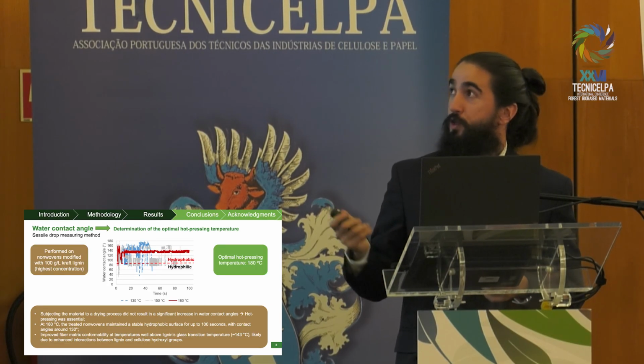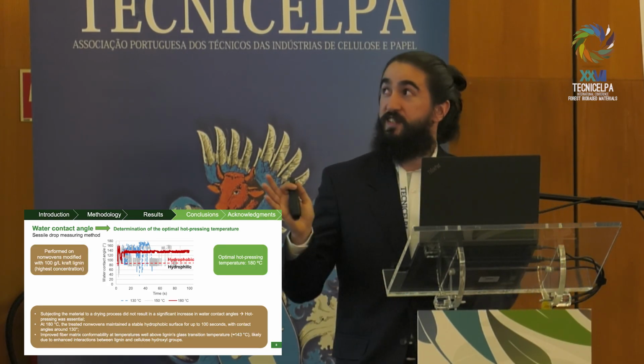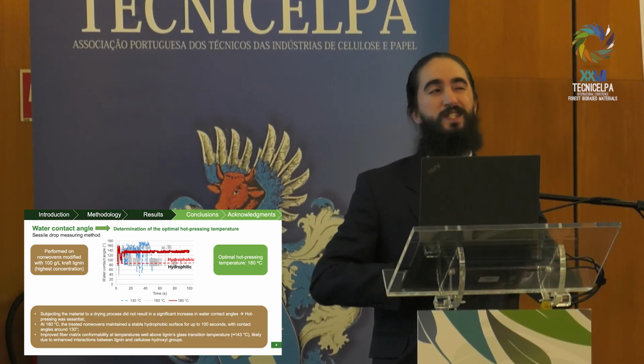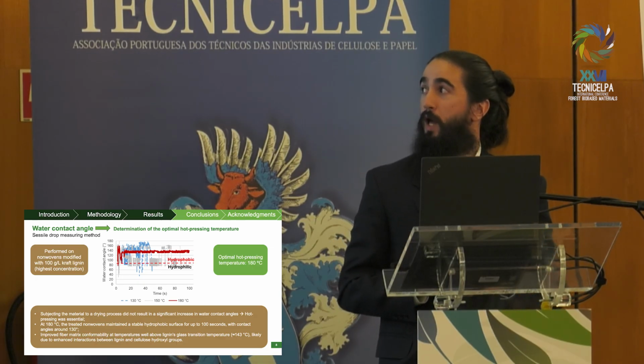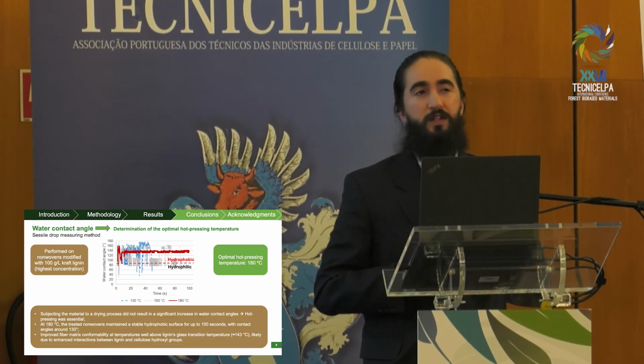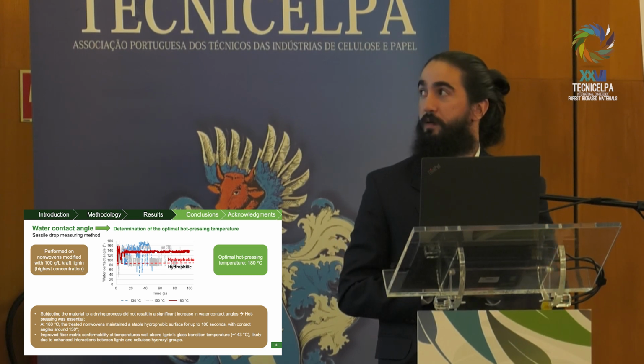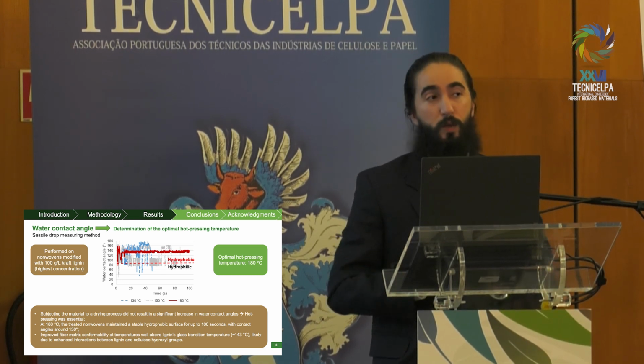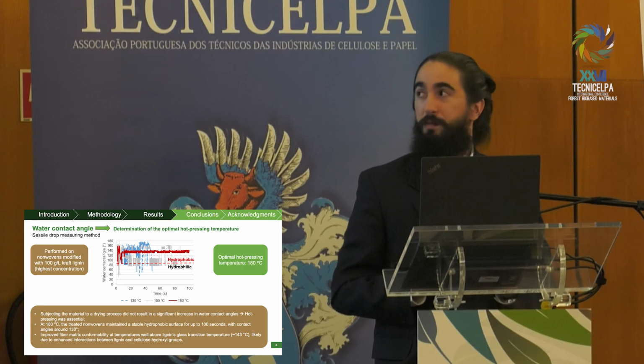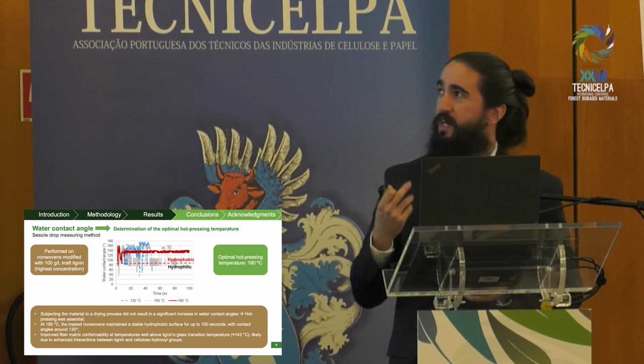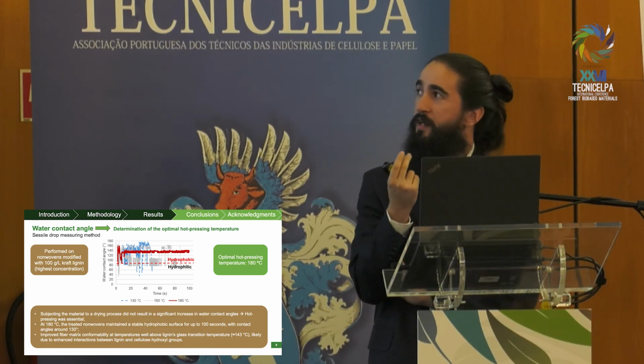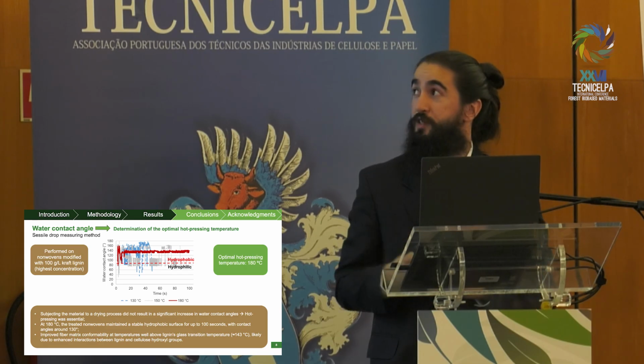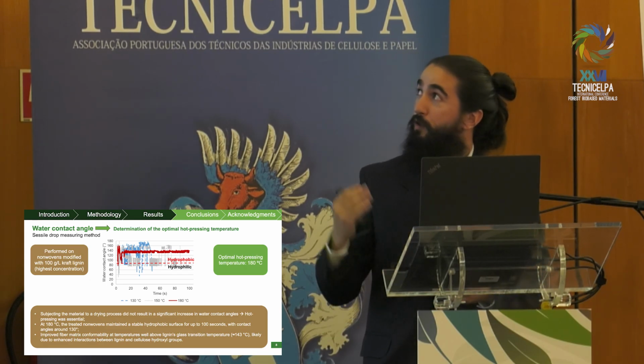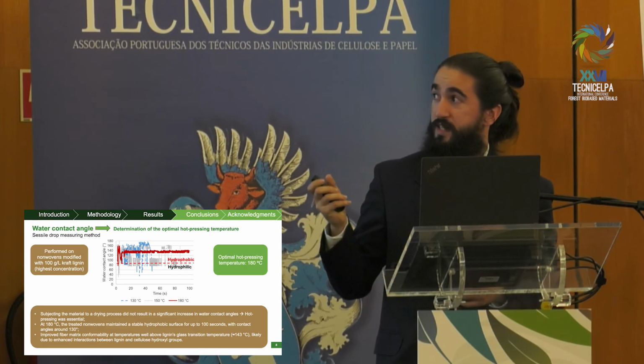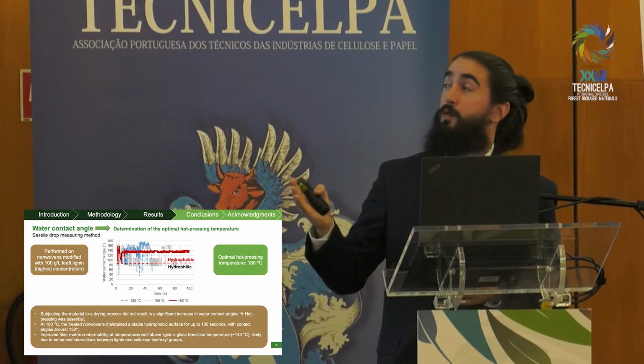Moving on to the water contact angle. First, in this slide, we want to assess what was the ideal hot pressing temperature and why. Initially, we didn't include the hot pressing in our procedure, but even by adding the lignin, we couldn't obtain hydrophobicity. So we started thinking, what can we do? Is there any process that is already used in industry that we can apply? And we thought of the hot pressing. In this case, we tested three different temperatures with these several measurements.